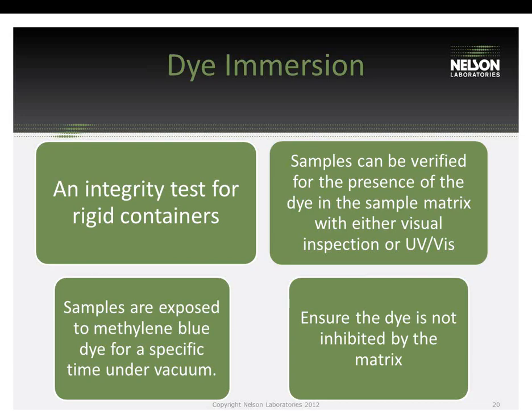One of the key notes to performing this test is to make sure that the contents of your product are not inhibiting the dye. So making sure that when the dye comes in contact with your product that it doesn't change the dye to create a false negative. An example of this would be tartaric acid. It turns the dye clear so it looks like you actually passed the test. So if you have products that are affecting the dye, this is not an appropriate test.